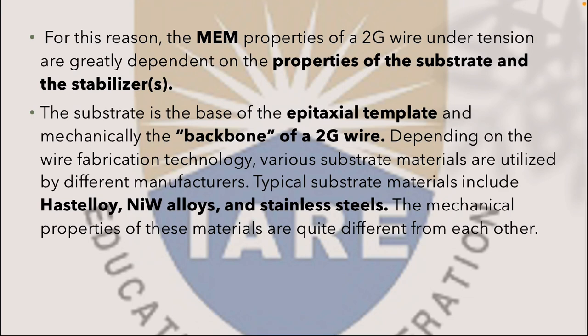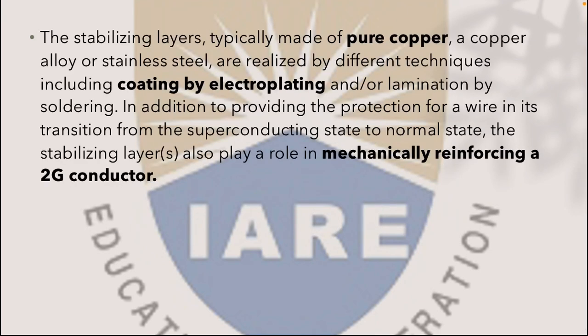Depending on the wire fabrication technology, various substrate materials are utilized by different manufacturers. Typical substrate materials include Hastelloy, NiW alloys and stainless steel. The mechanical properties of the materials are quite different from each other. The stabilizing layer, typically made of pure copper, a copper alloy or stainless steel, is realized by different techniques including coating by electroplating or lamination by soldering. In addition to providing protection for a wire in the transition from the superconducting state to the normal state, the stabilizing layer also plays a role in mechanically reinforcing 2G conductors.